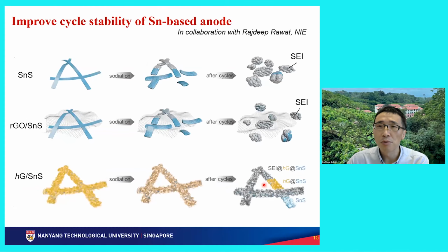So also 2 years ago, our group collaborated with Professor Rajdeep Rawat in NIE to extend the cycle life to 1,500 cycles rather than just 200. So how do we do it? We still start with the tin monosulfide nanobelts. We grow them by hydrothermal methods, into large grass-like structures. And this one is not a big deal. Everybody can do it. A lot of reports already.